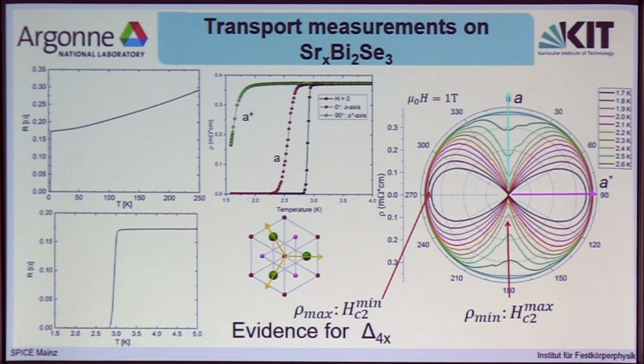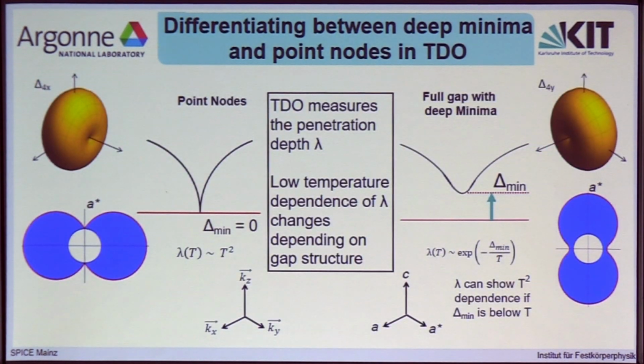And for this, there's a certain technique which is very well suited, and this is TDO, tunnel diode oscillator measurements. Tunnel diode oscillator measurements measure the penetration depths of a superconductor, and by the low temperature behavior of the penetration depths, we're actually able to say something about the superconducting gap structure.